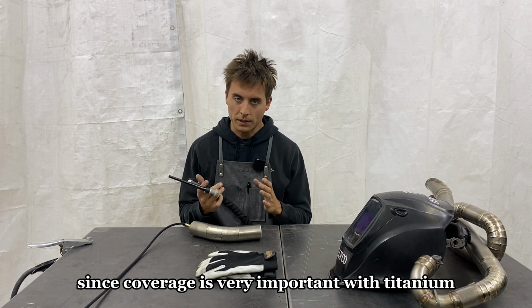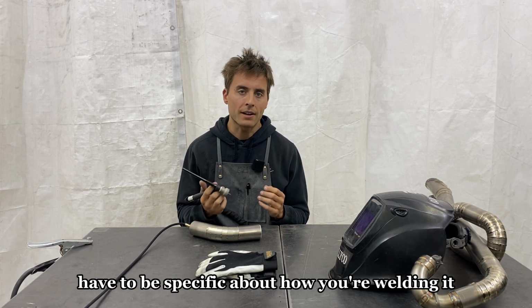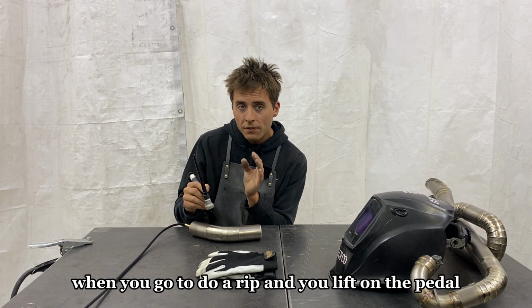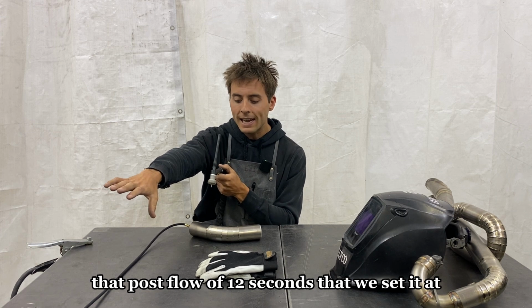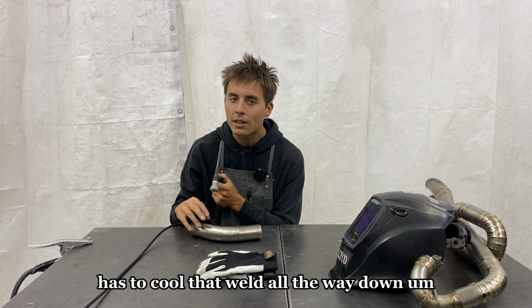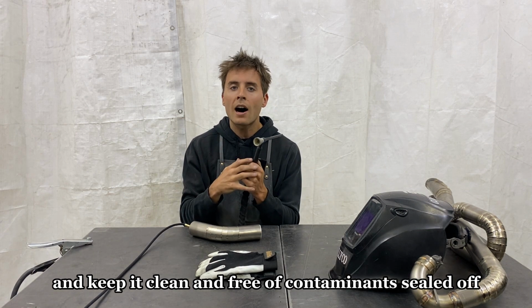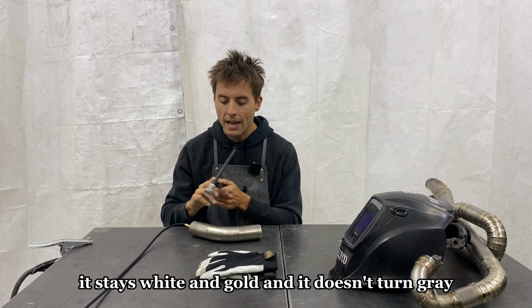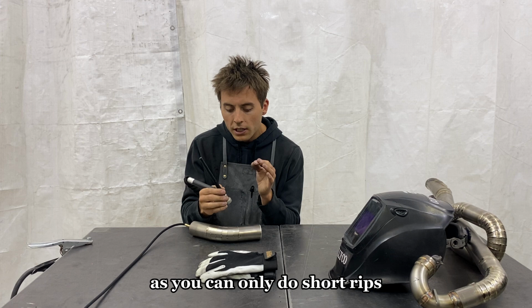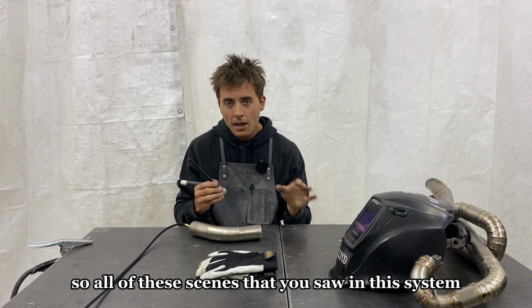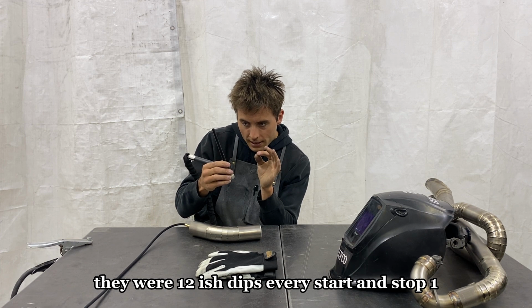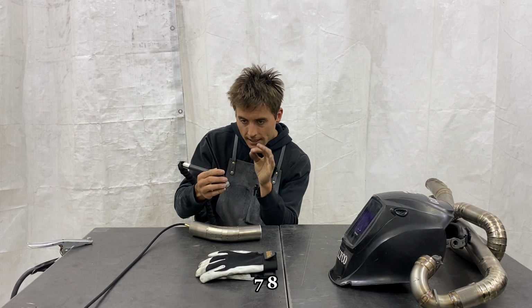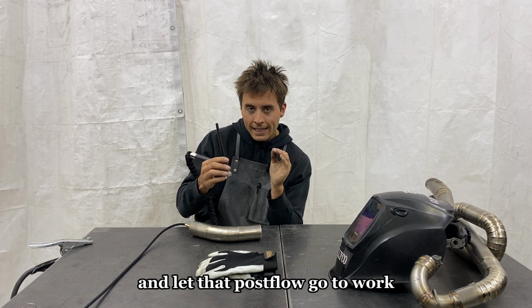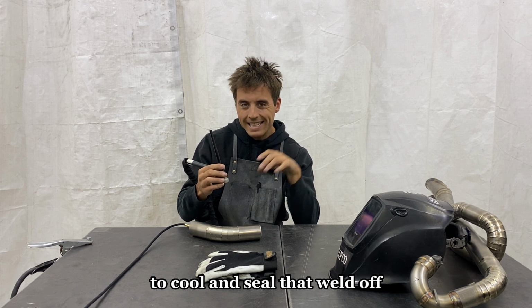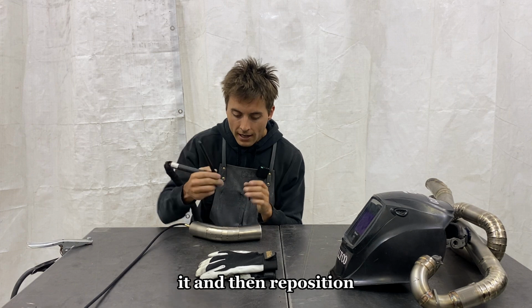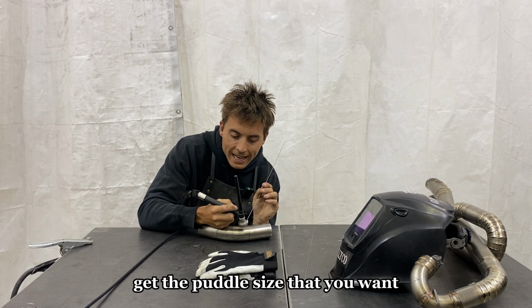Since coverage is very important with titanium, like we talked about, you have to be specific about how you're welding it. When you go to do a rip and you lift on the pedal, that post flow of 12 seconds that we set has to cool that weld all the way down and keep it clean and free of contaminants. It's sealed off, it stays white and gold and it doesn't turn gray. When welding titanium, this is kind of the downfall, is you can only do short rips. So all of the seams that you saw in this system were 12-ish dips every start and stop. 1, 2, 3, 4, 5, 6, 7, 8, 12, and then lift the pedal and let that post flow go to work to cool and seal that weld off and make sure that it doesn't get any contaminants in it. And then reposition. Go to strike that arc, get the puddle size that you want.